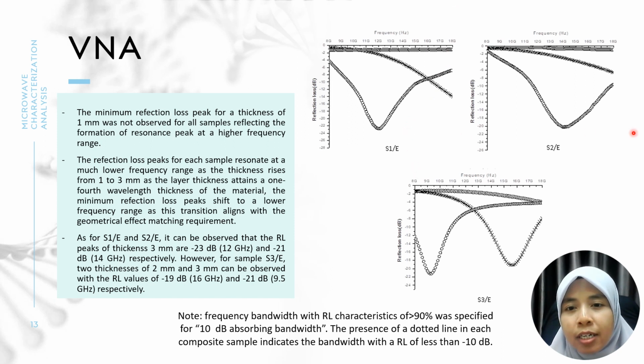So as for S1E and S2E, it can be observed that the RL peaks of thickness 3 mm, this one, are negative 23 dB at 12 GHz and negative 21 dB at 14 GHz respectively. However, for sample S3E, we could observe for thickness 2 mm and 3 mm at different frequency with different reflection loss. So actually, in the whole sample, we mix with epoxy resin as the matrix. Epoxy composites actually play a critical role in the absorption of EM wave by absorbing the EM wave energy and mitigating the radiation. This event occurs via the interaction between interior electrons and exterior EM wave radiation and inner electrons of the epoxy composites. So actually, a reflection loss value of less than negative 10 dB shows that the sample effectively absorbs the EM wave signal.